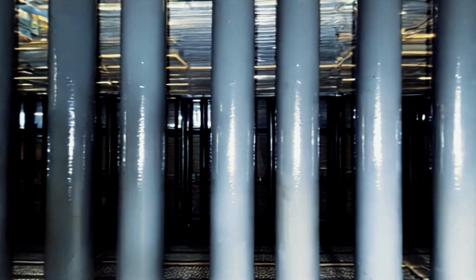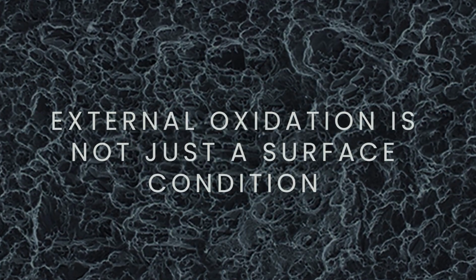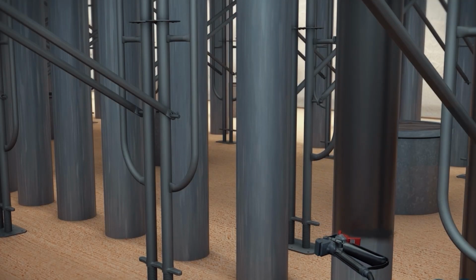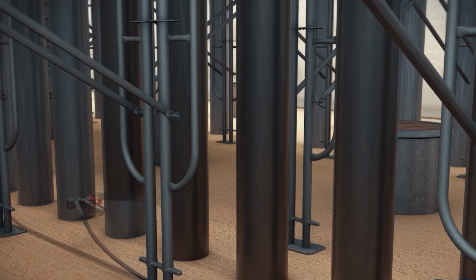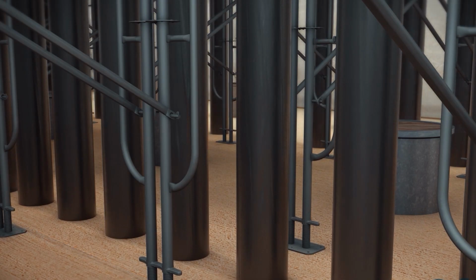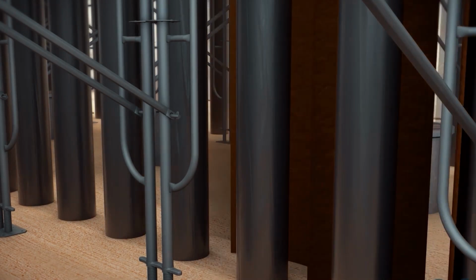and the compounding effect. So in summary, external oxidation is not just a surface condition. It's not something to be tolerated in the headwinds of operational efficiency. This is a way that oxidation stops your heat transfer efficiency. It can give you misleading temperature readings, certainly puts you on the path to increasing firing, elevates your metal stress, accelerates tube wall loss. All of that is unnecessary by applying C-Tech ceramic coatings because they're designed to minimize those effects over years of stable operation.